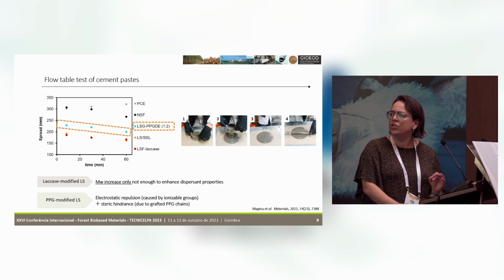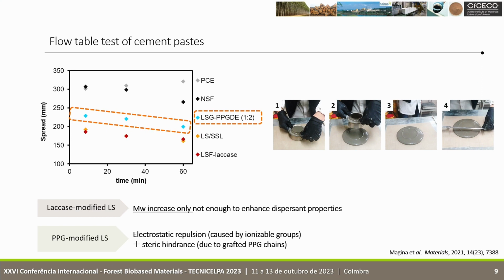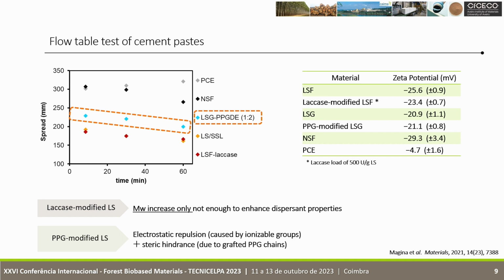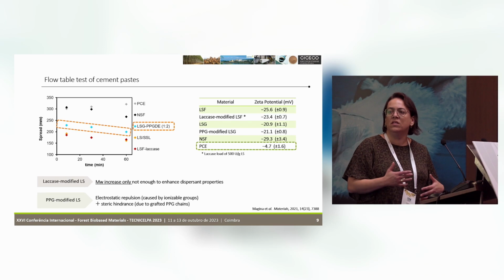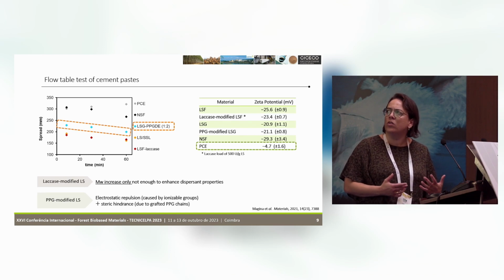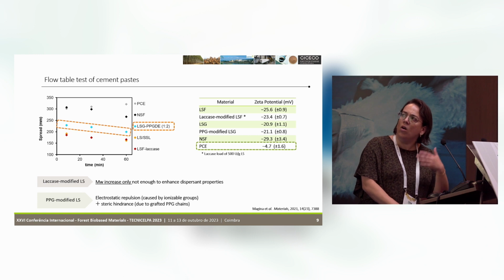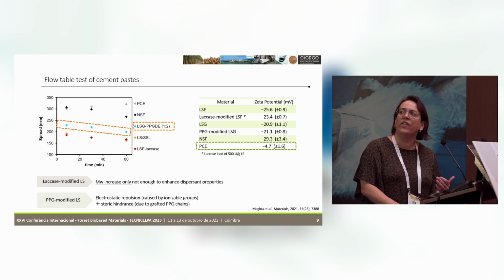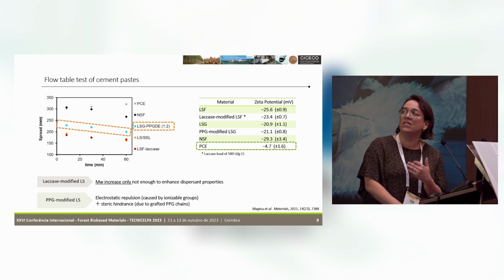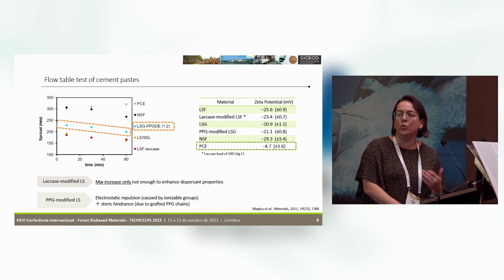I only want to show additional results related to zeta potential values. For those who work with this subject, you'll find in the literature that they state zeta potential values are enough to determine the dispersant properties of this type of product. As you can see from the results, all lignosulfonates, modified or unmodified, have similar zeta potential values, such as the naphthalene-based condensate, which is a superplasticizer. This shows that these values are not enough to assess the dispersant properties of this type of product.